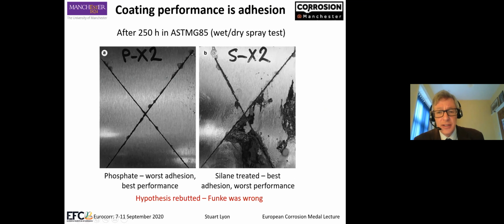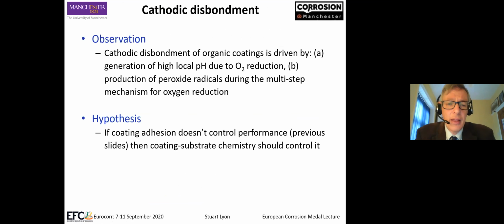And in fact, the paint has almost completely delaminated in here. It's just holding on by the skin of its teeth, as we say. So after 250 hours in a wet dry salt spray test, we can easily rebut the adhesionist performance hypothesis. Funke, in that case, was wrong. So if coating adhesion doesn't control performance, then what does control, particularly, cathodic disbondment performance?